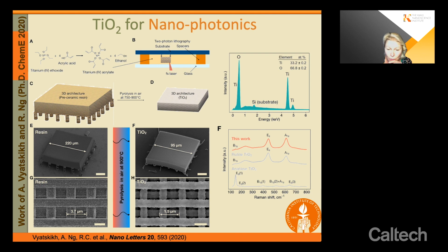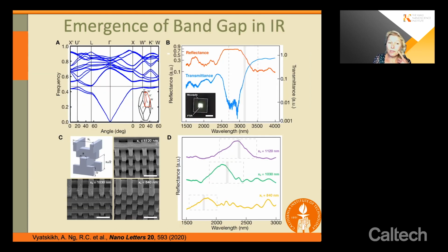You can see a woodpile architecture here with a periodicity of about 1.5 microns. Well, titania has a band gap that emerges in the infrared. And so what we're showing you here is the band diagram that was both computed and measured using the Fourier transform infrared detector. It shows the emergence of a band gap, where the wavelength is shifting with the periodicity of this woodpile architecture. So it's paving a way to create nanophotonic crystals using this type of additive manufacturing and chemical synthesis approach.